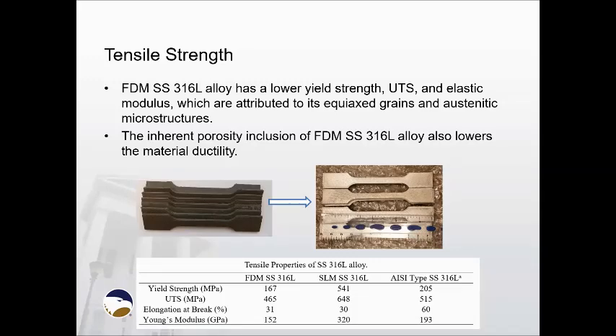465 megapascal, and I assume this tensile strength is attributed to the microstructure, the isotropic microstructure, as well as the porosity inclusion in the part, because there's always porosity in the FDM part. The defects cannot be eliminated after the debinding and sintering process.